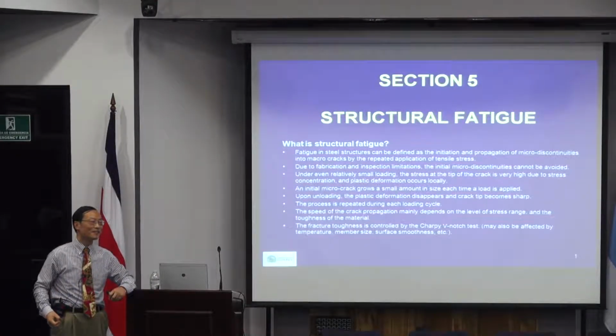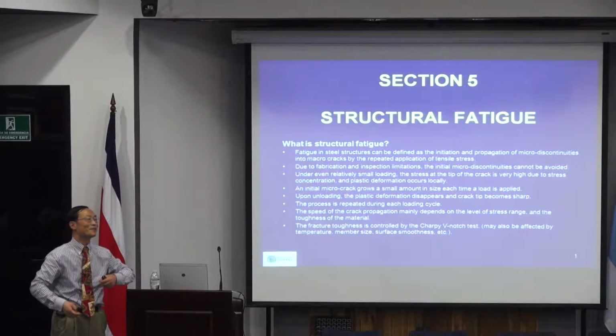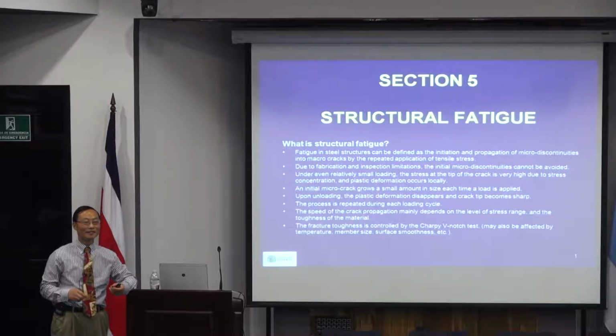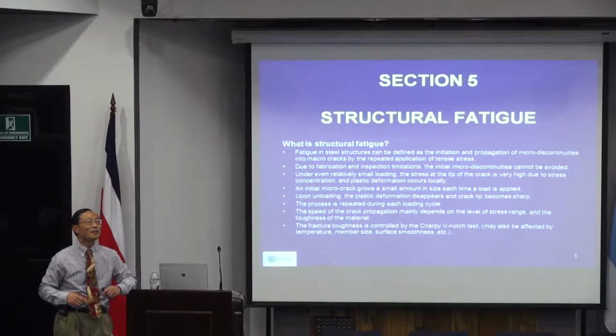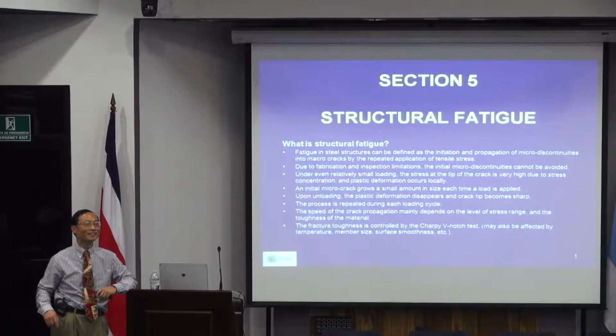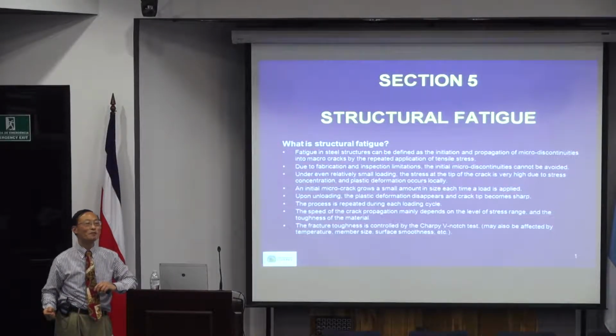And we know that since that's the natural process and you cannot avoid it, especially for bridges designed for truck traffic, and trucks come and go, not like a building, where if you design for a library, you put a box there, and that box will sit there for 20 years, so you don't have cycles. So that's typically the problem of bridges, and especially highway bridges. For railway bridges, we have trains, but we don't have thousands of trains per day. So the bridge life is very similar, about 75 years or 80 to 100 years. But railway bridges don't have that many trains per life, so they cannot accumulate that much energy to cause a fatigue crack. That's why we typically don't see any fatigue problem for railway bridges.